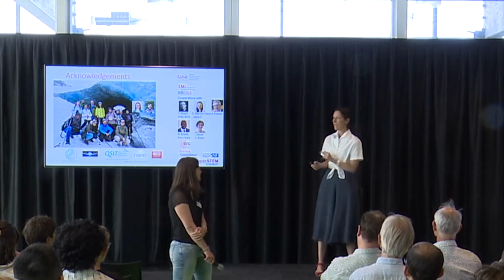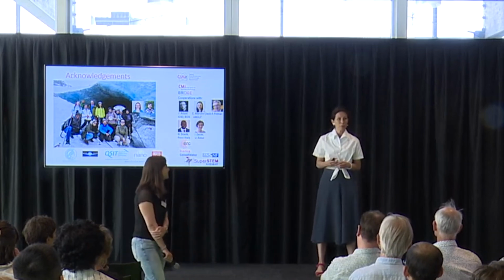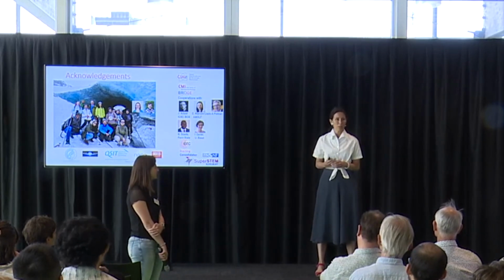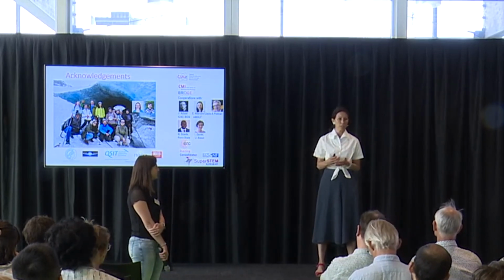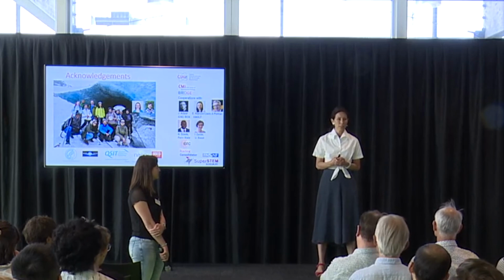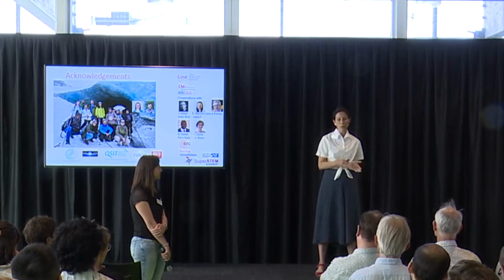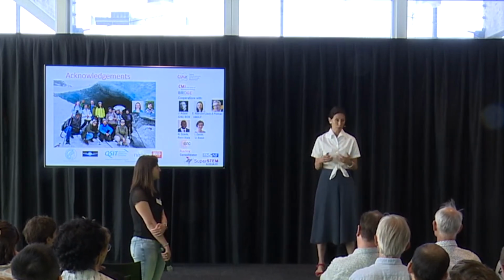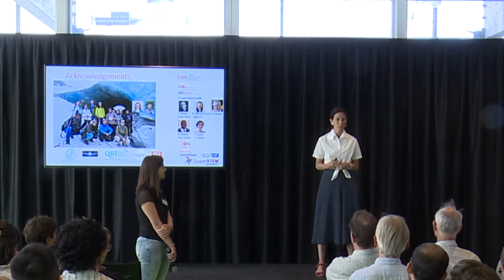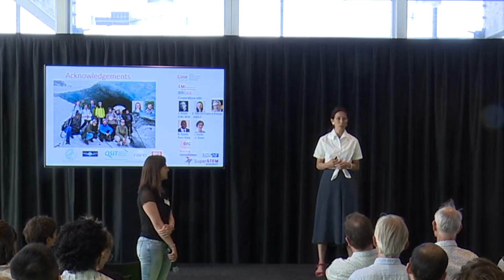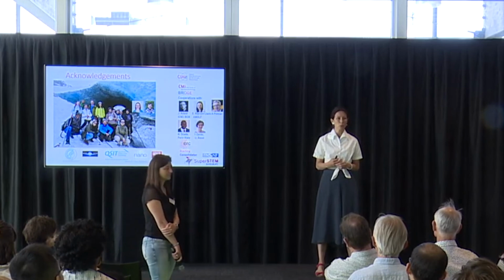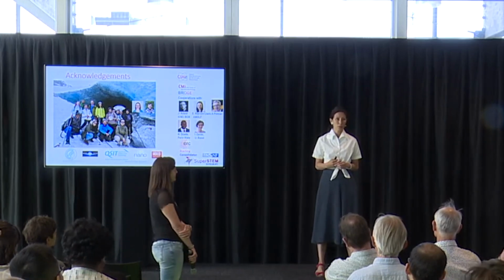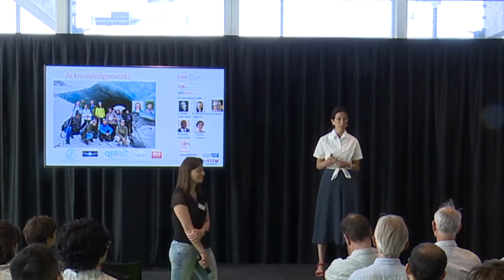One thing I didn't say is that for this device I showed, we started with the worst material we have, which is polycrystalline zinc phosphide. Then we went to monocrystalline, expecting better. In fact, not. The polycrystalline gives better results. So there is something to understand there too, why a polycrystalline material gives much better carrier collection than the monocrystalline.